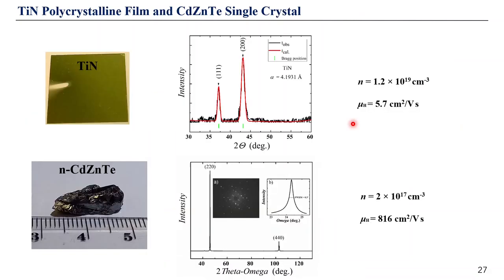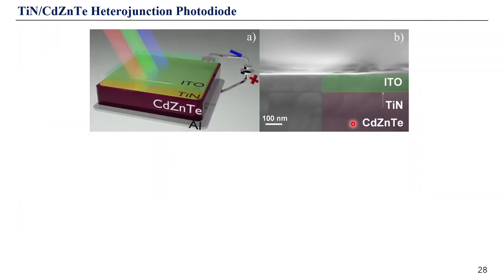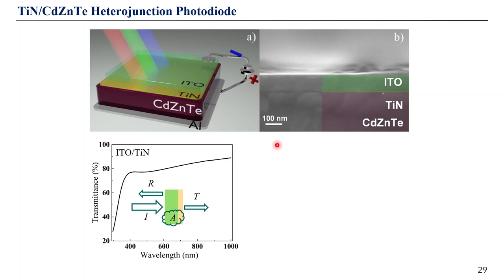So my idea was to combine polycrystalline magnetron sputtered titanium nitride thin films with single crystal cadmium zinc telluride substrates in order to fabricate a heterojunction which hopefully is possible to optimize to get high performance photodiodes, and then this type of device is expected to have a high radiation resistance because it is based on two radiation-resistant optoelectronic materials. So that is the device structure we made in our lab, and the cross-section SEM image of this device structure. In order to get decent optical transmittance for the window layer, we used a sandwich of ITO about 100 nanometers and titanium nitride 10-15 nanometers. So we reached the level of 80% transmittance in a wide spectral range.